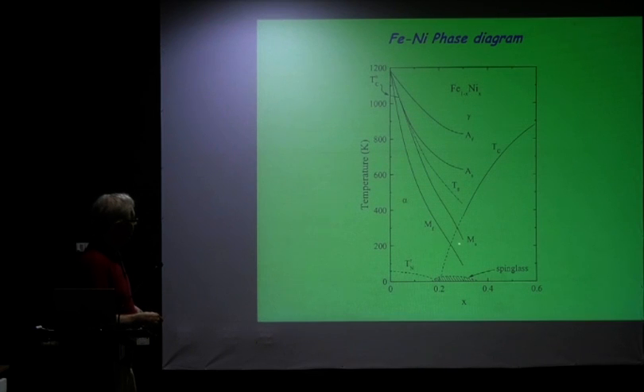Now, when we go back and look at the phase diagram of iron nickel, this is just to show you what range we did the thermal expansion measurements. All up here, in pure iron, we have a Curie temperature which was here, and this is all gamma FCC, and as you add nickel, we get martensitic transitions with very broad hysteresis. So you have a martensite start temperature here, finish temperature here. You come into the martensite state.